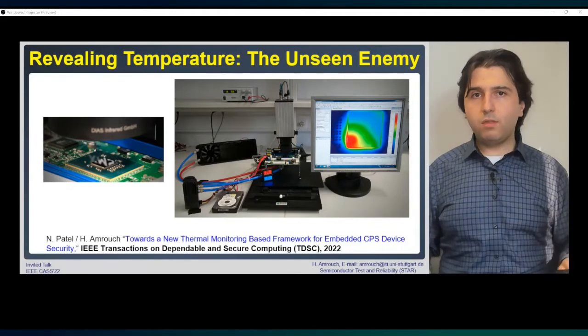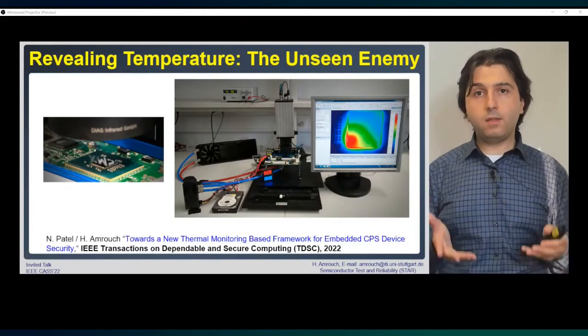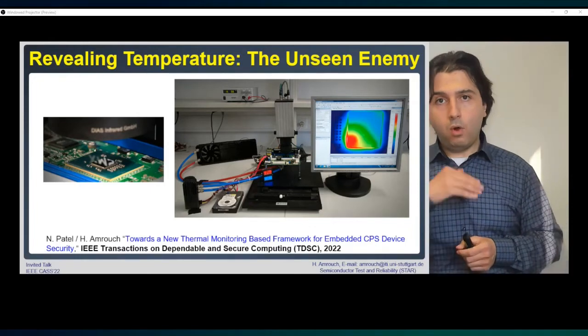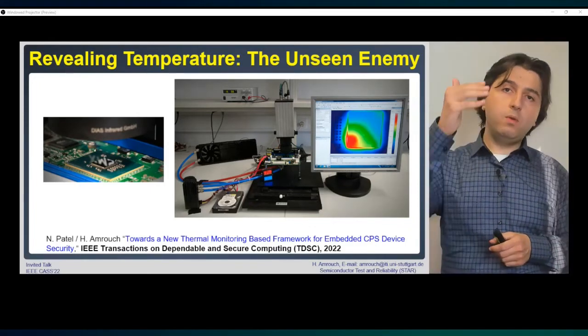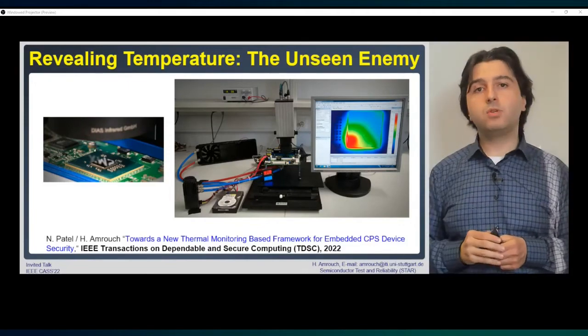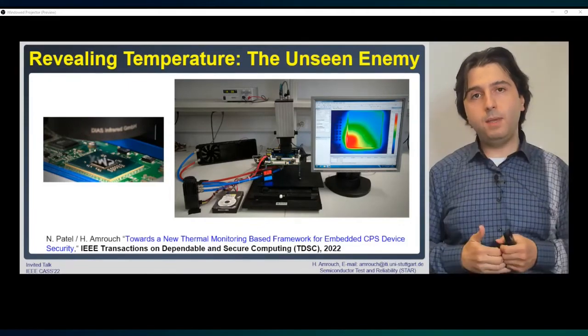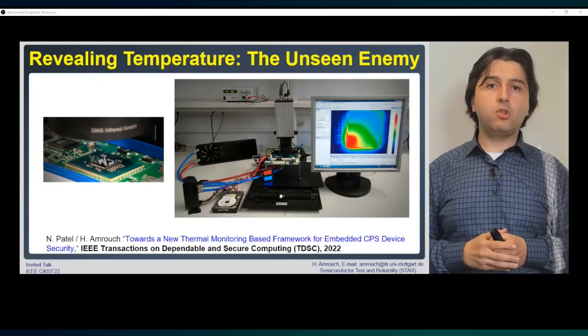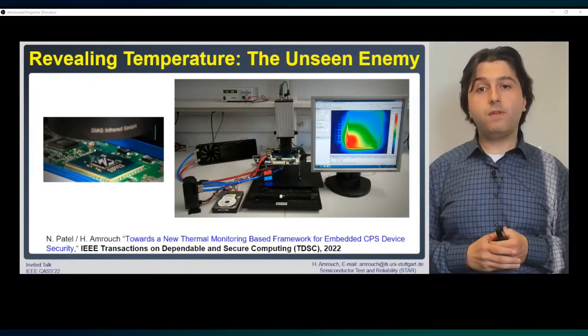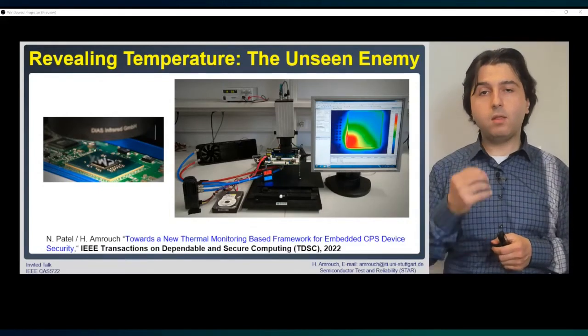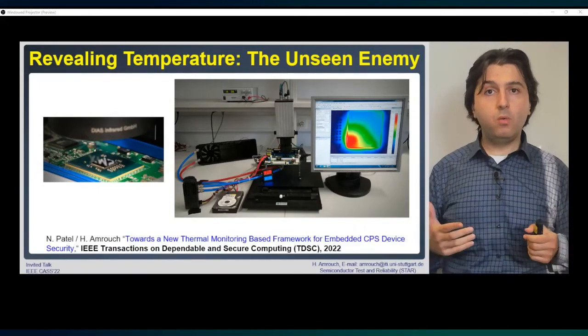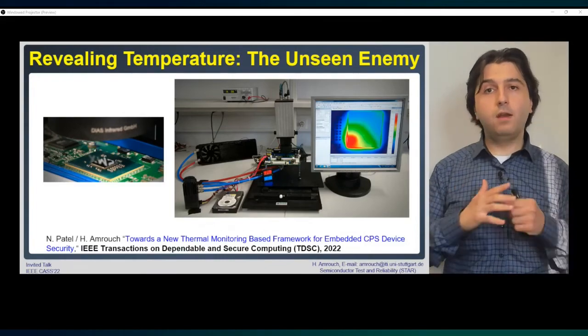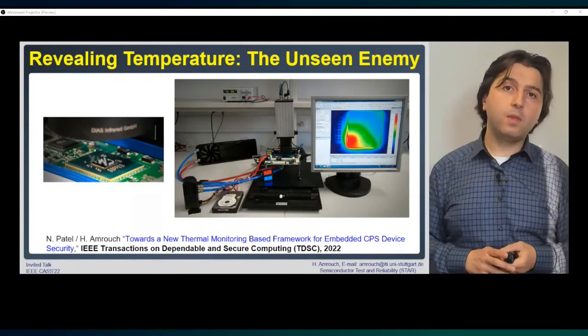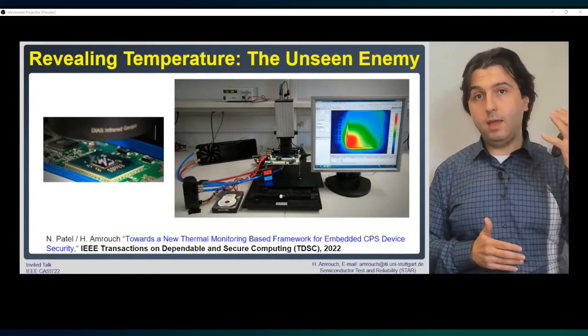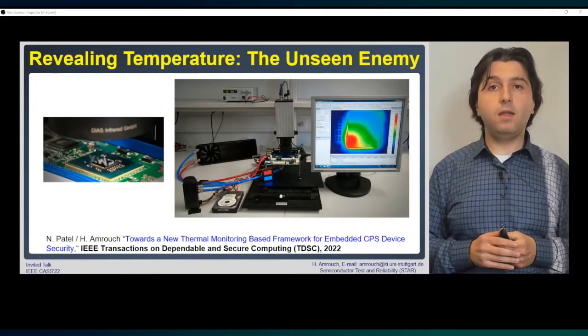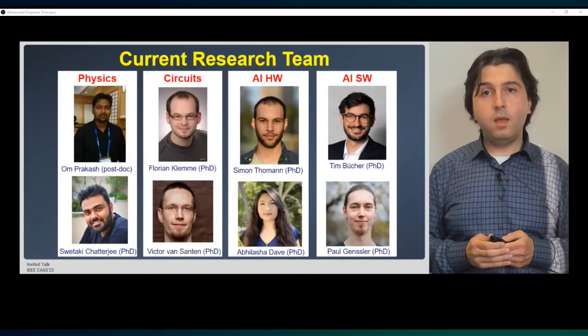We achieve that by applying concepts of the Peltier effect and thermoelectric effect on the bottom side of the chip, in which we are dissipating the heat coming from the processor through the bottom side, or through the PCB, instead of the top side as done traditionally. And this again allows, for the first time, capturing a very accurate thermal image of processors without any layer or package interfering between the infrared camera and the underlying chip under measurement. This brings me to the end.